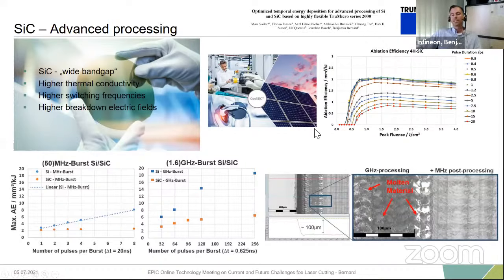But due to the flexibility that TRUMPF offers, it gives you the possibility, for example, to use both worlds. You can do a fast ablation rate scan with gigahertz processing, removing a lot of material. And then finally, you do the megahertz post-polishing. Then you can also achieve a very nice roughness. And you can see here, qualitatively, it looks very attractive.